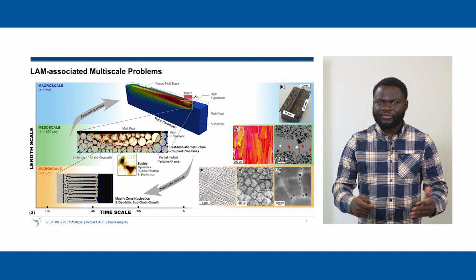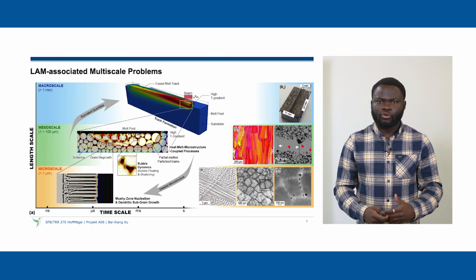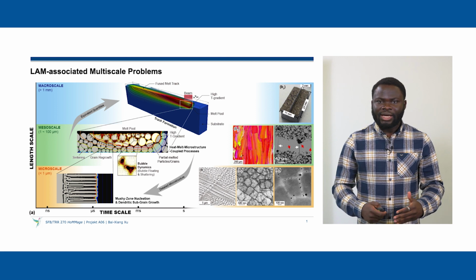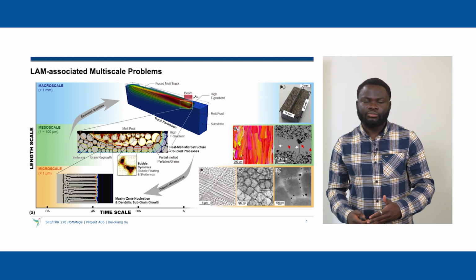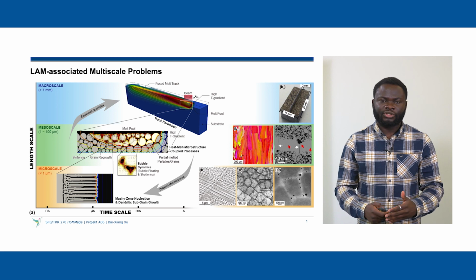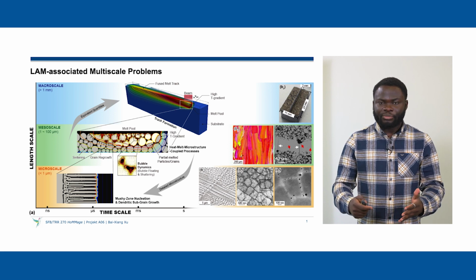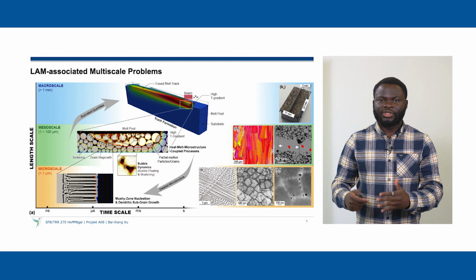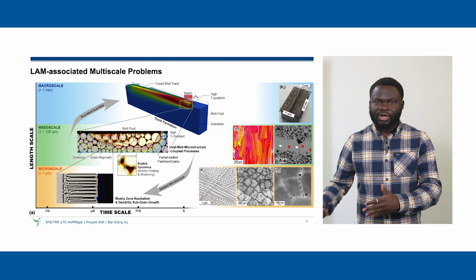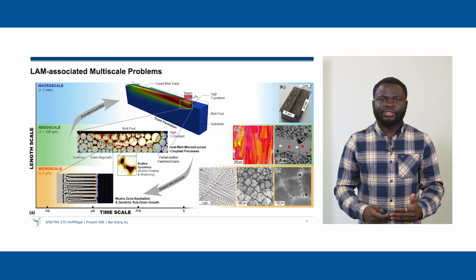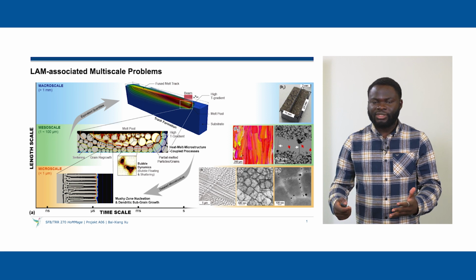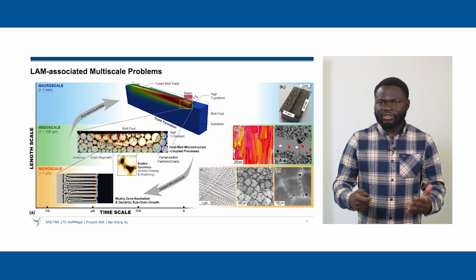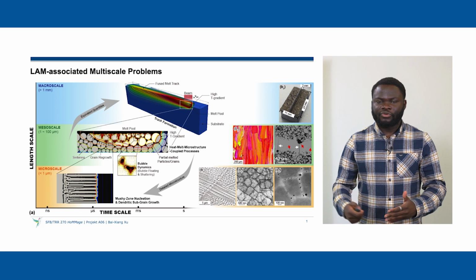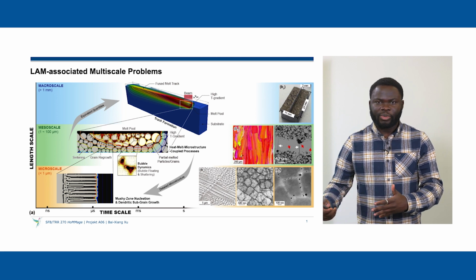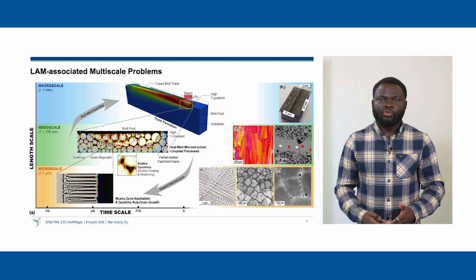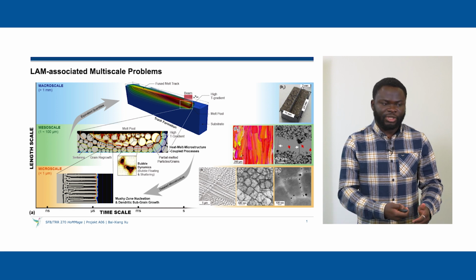on the mesoscale, for example, you have processes such as melt flow, solidification, grain growth, and on the microstructure features at this scale, you have features such as porosity, and due to high temperature gradients, sometimes you can also have thermal shock, which leads to cracks. On the micro scale, on the other hand, you realize that your grains are not fully dense. It's possible for you to have dendritic structure, and also it is possible for you to have segregation of solutes or nanoparticles in the grains or grain boundaries, which can also influence the magnetic properties of a material.